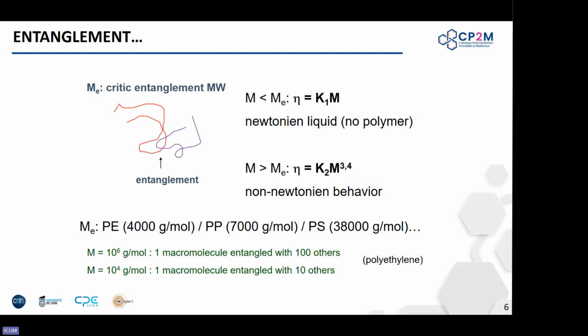A comment about entanglement. For polyolefins, the value of molar mass to reach the entanglement tends to be very low. So you get this semicrystalline polymer very early, okay, and that's a big advantage. So you'll get an entanglement for PE for something that most of you would qualify as, oh, it looks like an oligomer. 4,000 grams per mole is not a high number, but already you start to see something interesting, for instance, an HDPE of 4,000 grams per mole already has a melting point of almost 132, 133, so almost 135, okay?